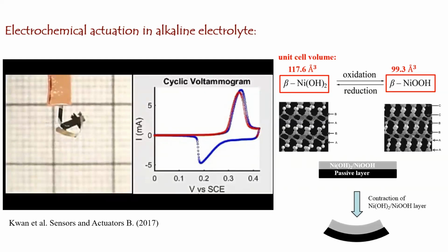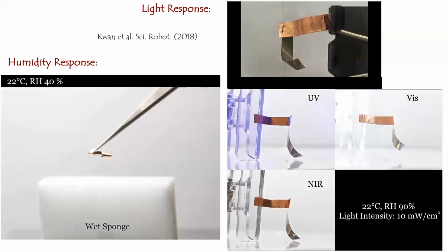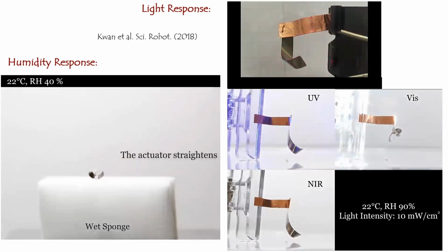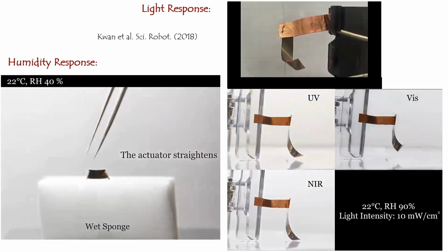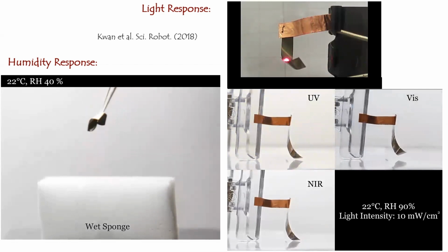So in this case, we have the active material coated on top of some passive layer. So when the top layer shrinks, it will curl up, as you can see. And when the voltage now enters the reduction range, it will flex back. So that is the electrochemical actuation. The same sample, you don't even need to produce another sample. You now lift it out of the liquid electrolyte just to put it into some atmosphere, like ambient atmosphere with some humidity or air environment.